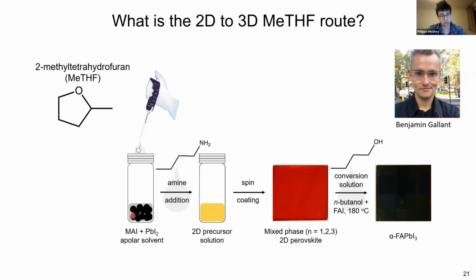And what we do is we have methylammonium iodide and lead iodide. And he adds the methyl THF, and it's an apolar solvent, so it's essentially just a suspension. So the powders are still black. It's not dissolving the powders, but only if one adds the amine. If one adds butylamine, the reaction between the Bronsted activity of the amine and the methylammonium causes the precursors to dissolve. So you get a 2D precursor solution. And then the moment we spin coat those, we get a mixed phase, a 2D perovskite, which is lovely red.